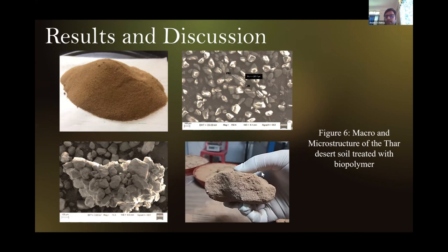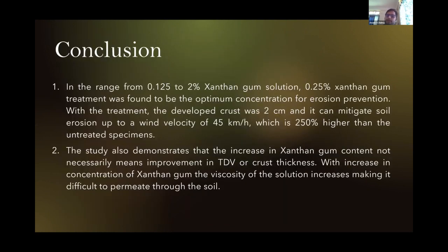We observed up to 3.5 millimeter of crust, which can be developed with these xanthan gum sprays. The major conclusion from this study is that in the range of 0.125 to 2% xanthan gum solution, which is a suitable range, 0.25% xanthan gum treatment is optimum, and it can develop a crust up to 2 centimeters, and it can mitigate soil erosion up to 45 kilometers per hour.